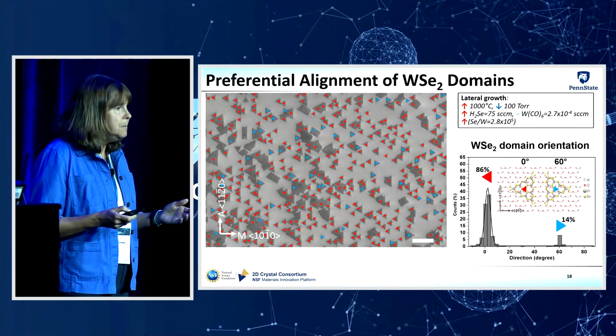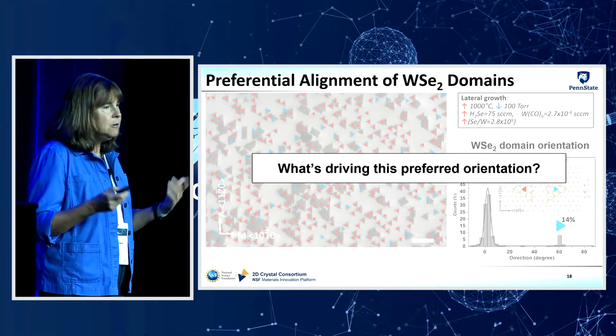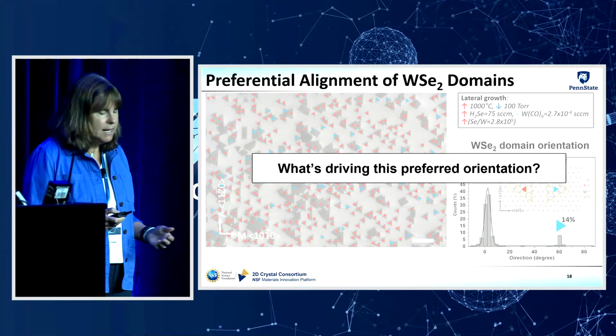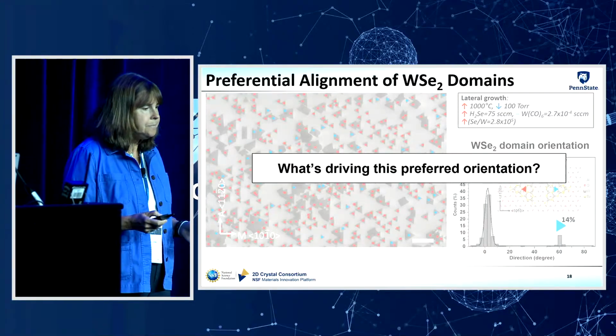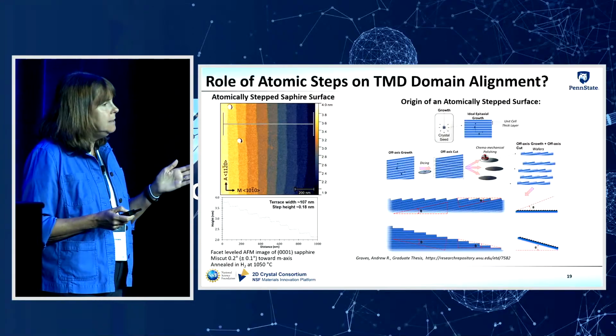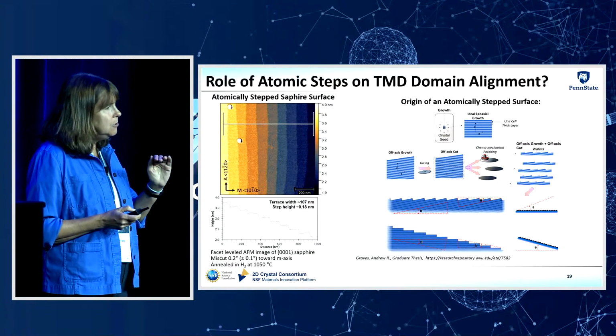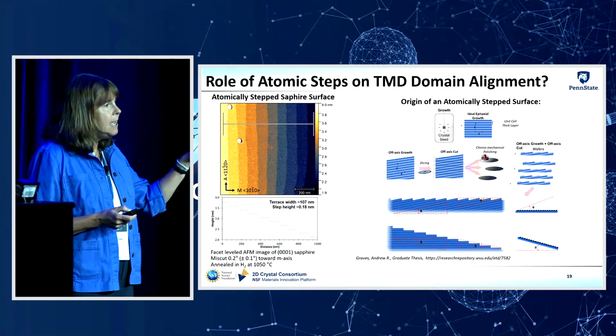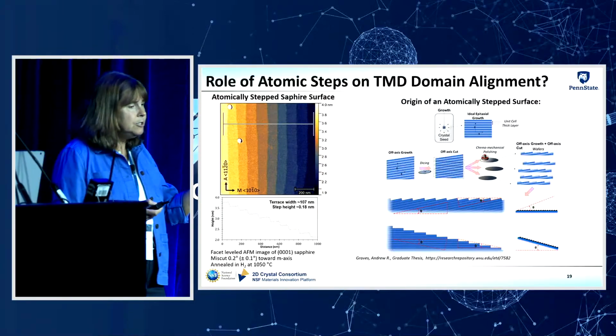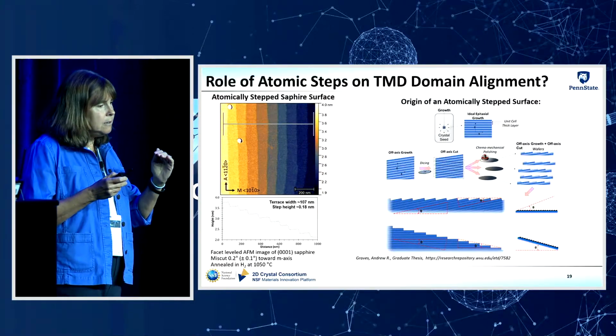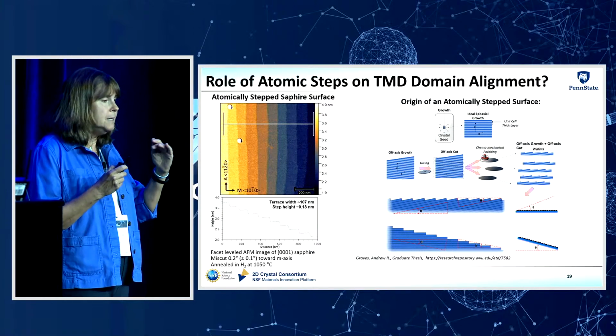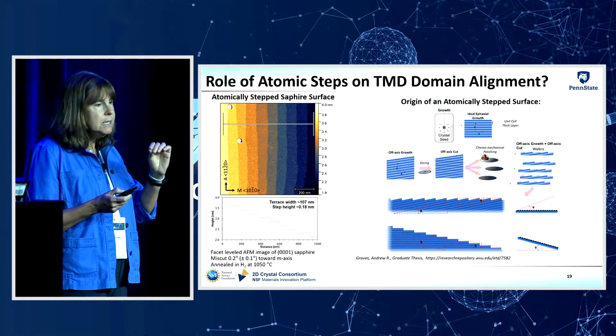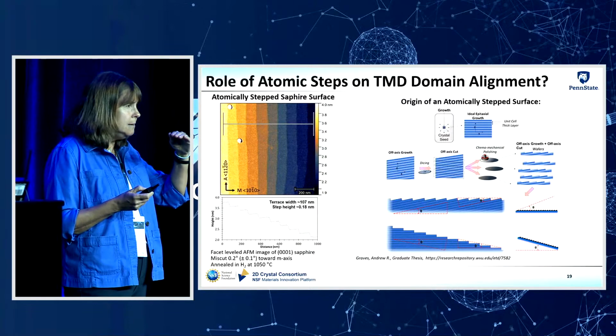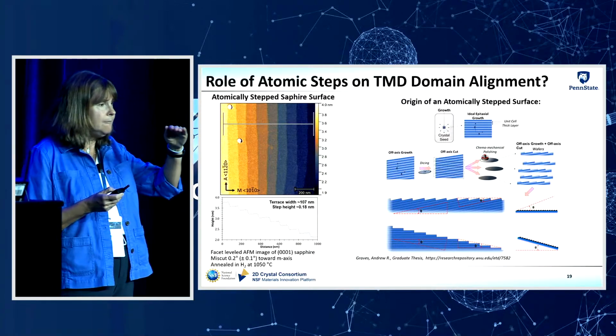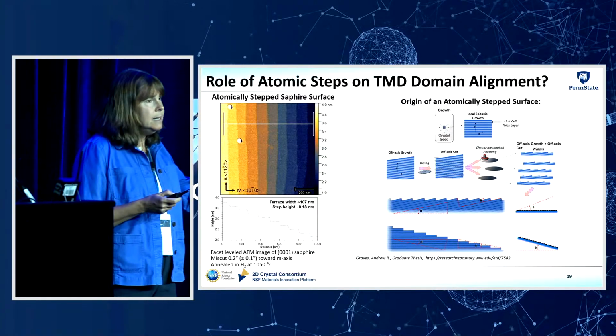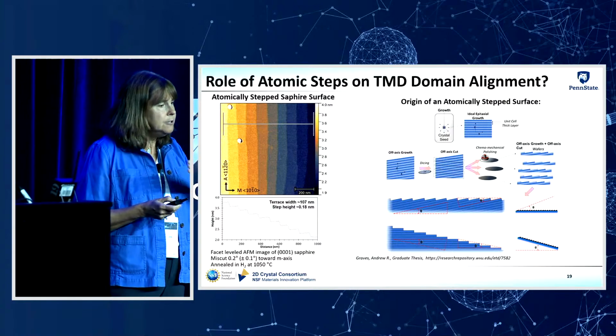So when we saw this, we were very excited, but the question is, what's giving rise to this preferred orientation? Now, I should mention that the sapphire substrates that we use aren't atomically flat. They have steps on them. This comes about because of the way the wafers are cut from the sapphire boule. You typically cut the wafers at a slight miscut off of a major crystallographic plane, and this results in periodic steps on the surface.